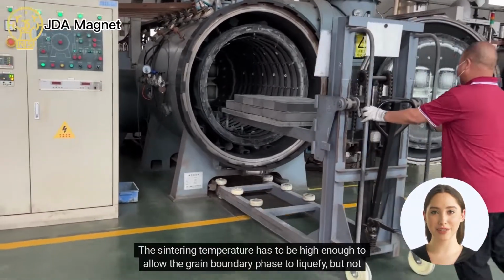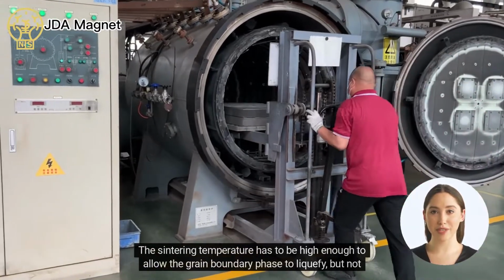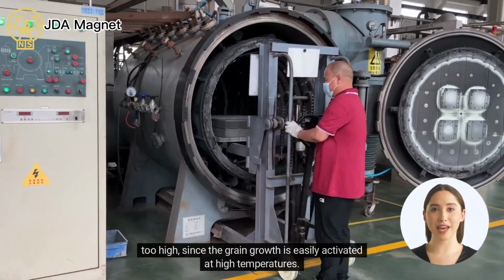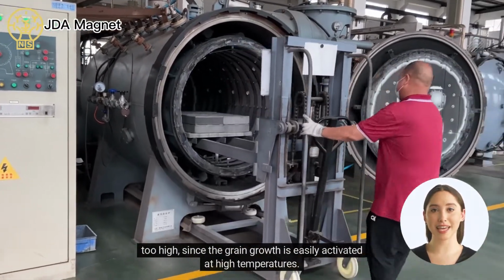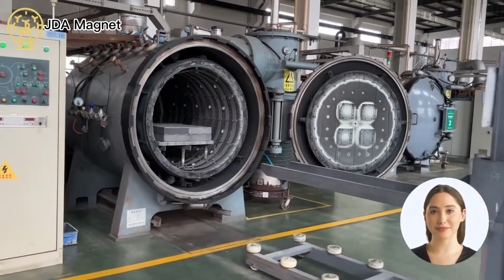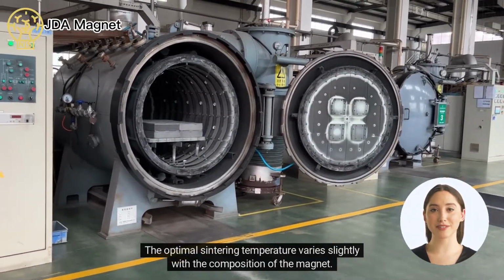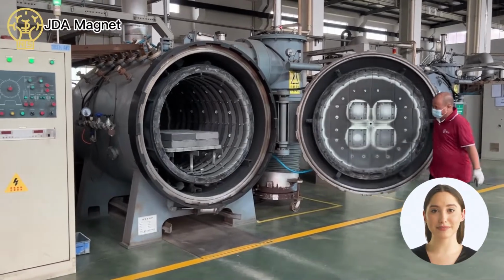The sintering temperature has to be high enough to allow the grain boundary phase to liquefy, but not too high, since the grain growth is easily activated at high temperatures. The optimal sintering temperature varies slightly with the composition of the magnet.